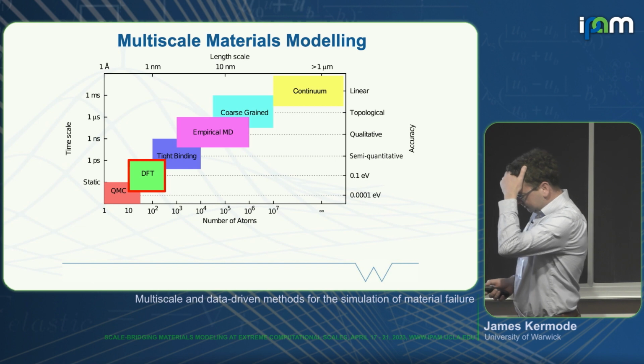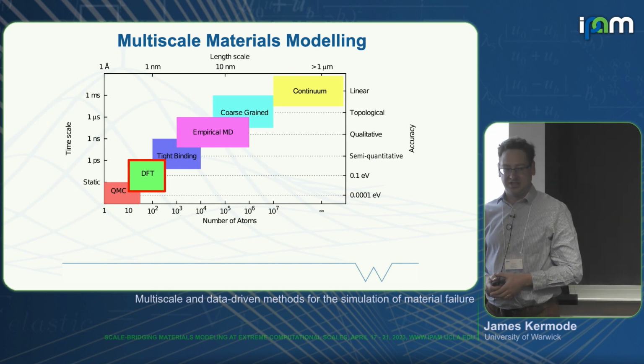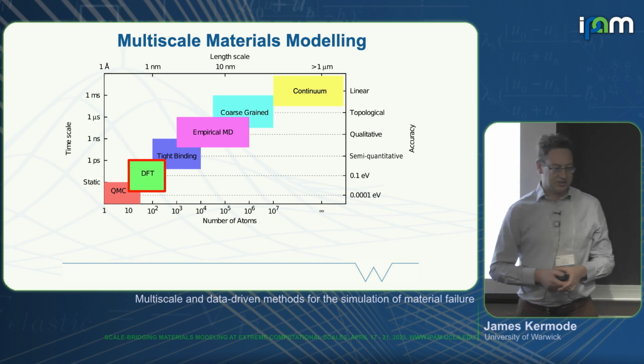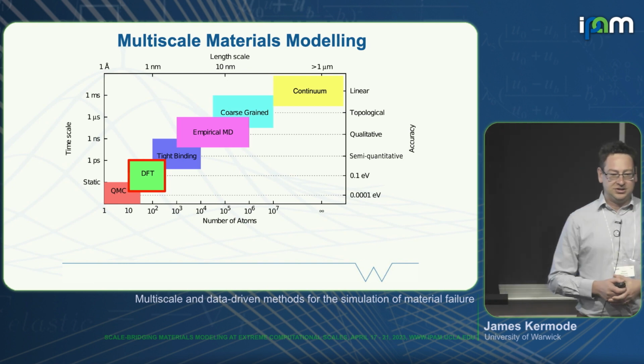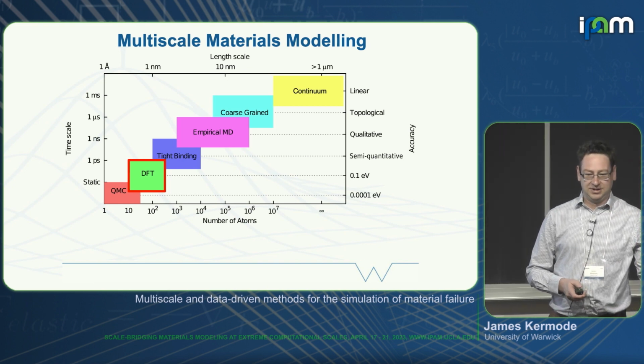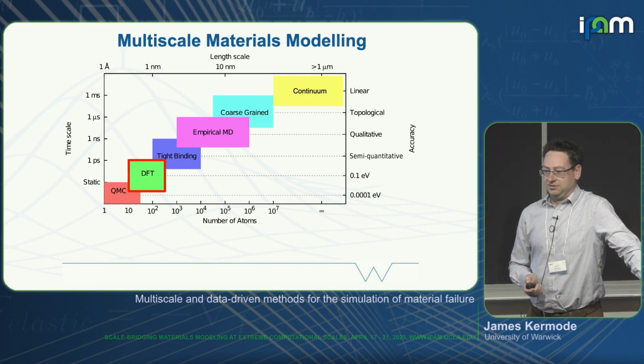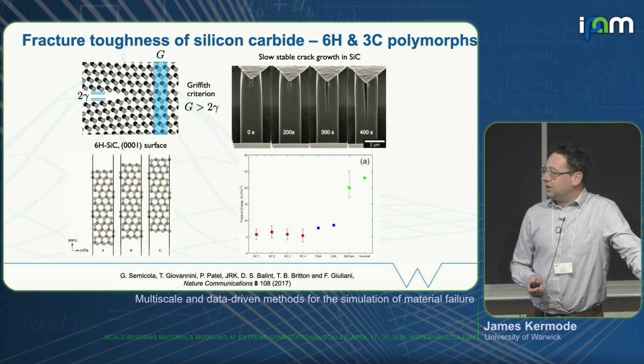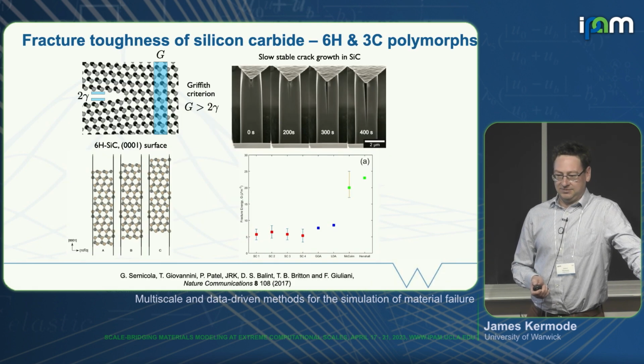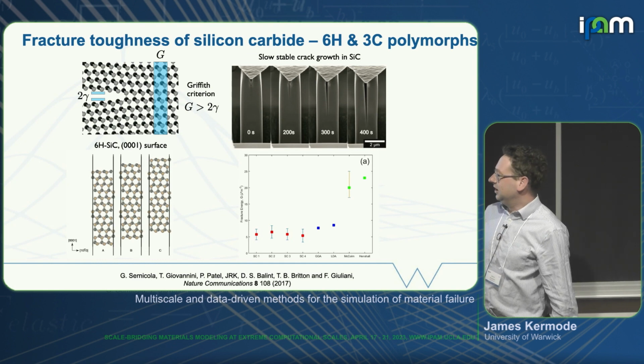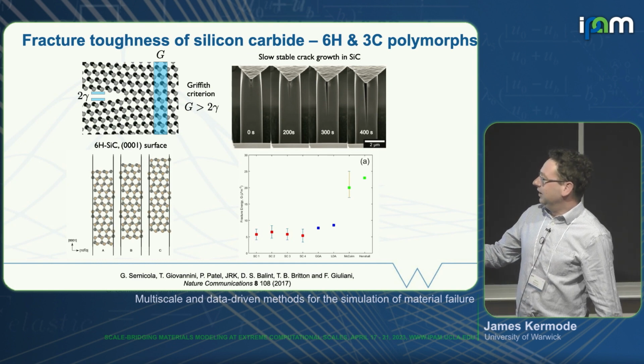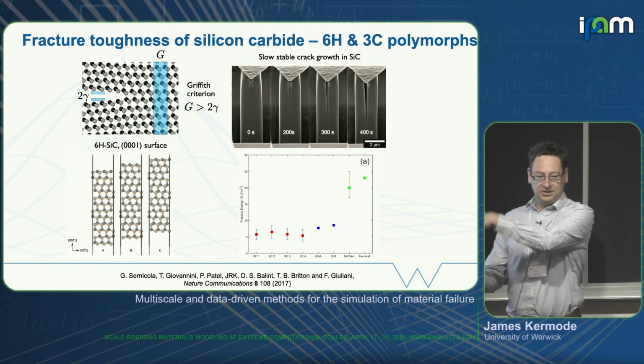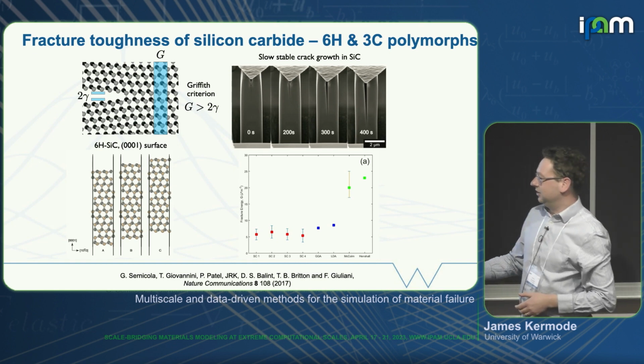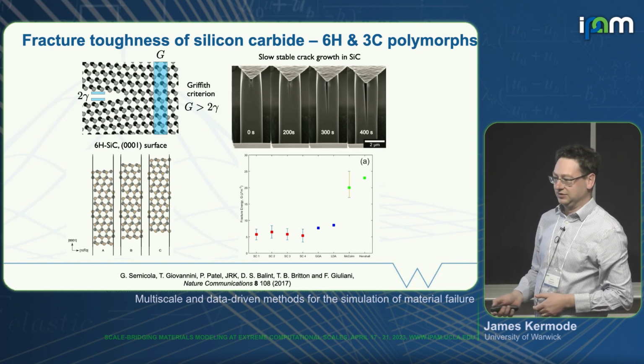We can make useful contributions to understanding material science using quantum mechanics alone, using density functional theory, if we choose the quantities that we calculate in a smart way. So again, thinking about fracture, we know that there's a global energy balance criterion going on. Griffith tells us that a crack moves forward if the energy that we relieve in some volume ahead of the crack tip exceeds the cost of creating two new fracture surfaces.